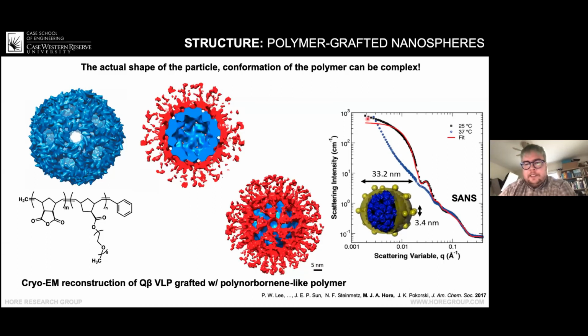And so when we originally did this experiment in particular, we noticed that we had this kind of shape here, if you see these peaks, that were due to the scattering of something that was spherical. But what we also saw was this foot here. And the slope of this line told us that what is on the outside of this sphere must be a compact object. So in some sense, it need not be spherical. I guess they could be triangles or something crazy, but it was telling us a bit more information just based on the slope of these things alone and where these different transitions took place.